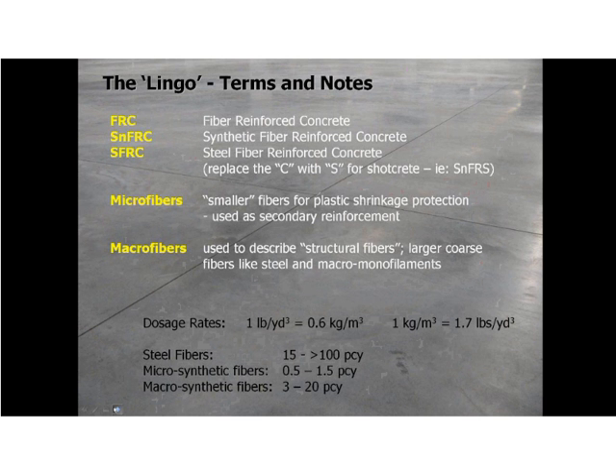When you look at macrofibers, some of the marketing folks have called these structural fibers over the years. These are engineered dose fibers that can be used to be an alternative material to steel, but typically the dosage rates will vary significantly. With steel fibers, anywhere between 15 to greater than 100 pounds per cubic yard in concrete, and in the macrosynthetics, 3 to 10 from a commercial standpoint, with dosages going as high as 20 pounds per cubic yard in some specialty applications.